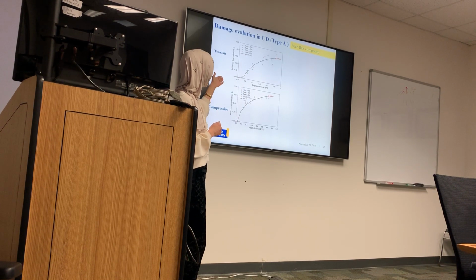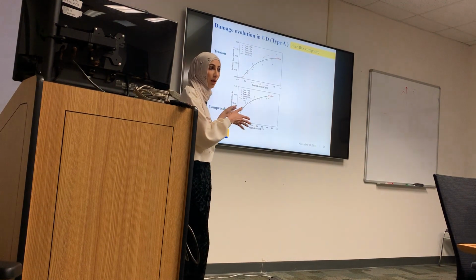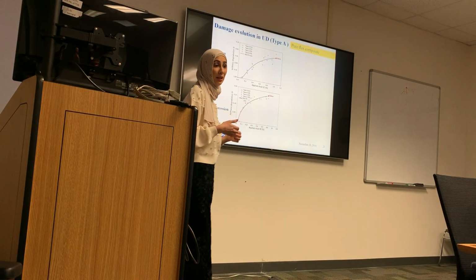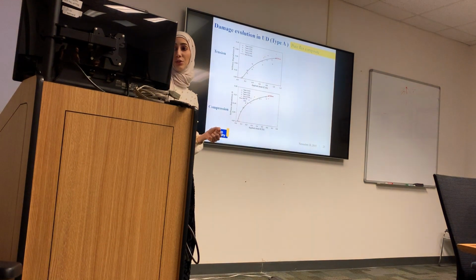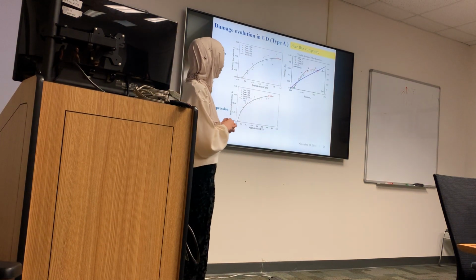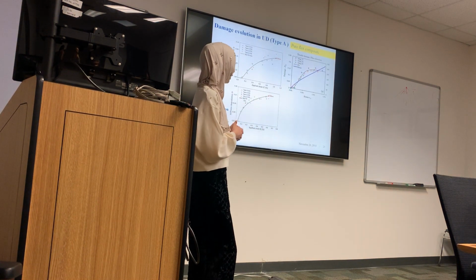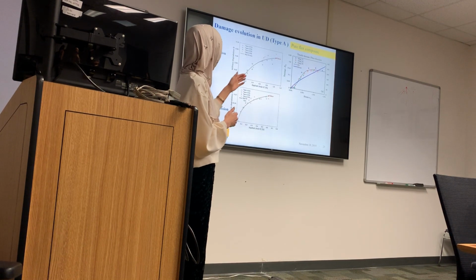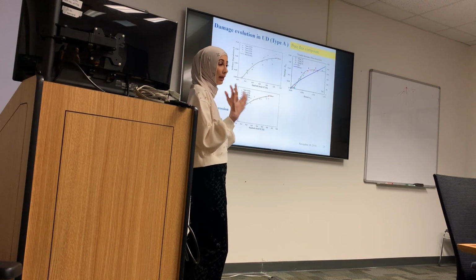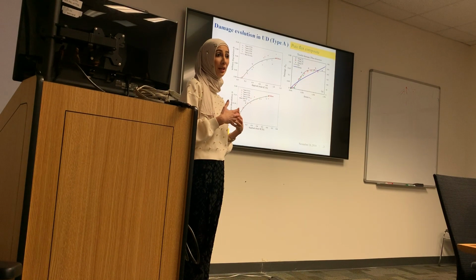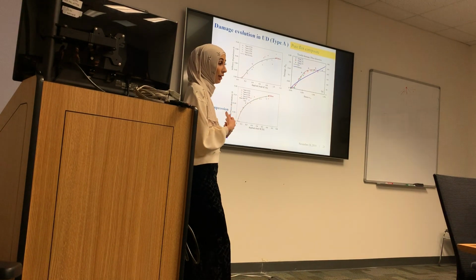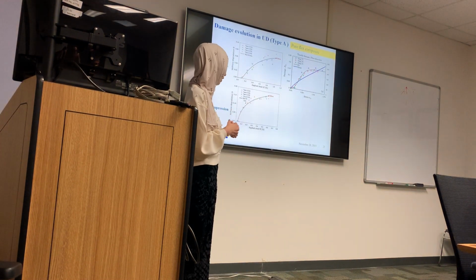We also try to compare what the hybrid composite that we have with an existing pure flax. So here from the literature, we see the profile that we got, the sigmoidal profile. It's similarly the same. That's only for us to give an indication that most of the damage was attributed by the flax fiber itself.